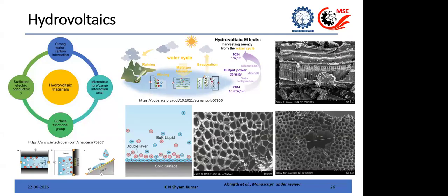Here, three things are important, I would say. One is the surface area of the carbon. The more the surface area, the more the interaction, and the more the possibility of forming a double layer. Second thing is the conductivity of the carbon, because the carbon has to conduct the electrons through it. So it has to be more conducting. Third thing is the availability of surface functional groups to interact with the water.